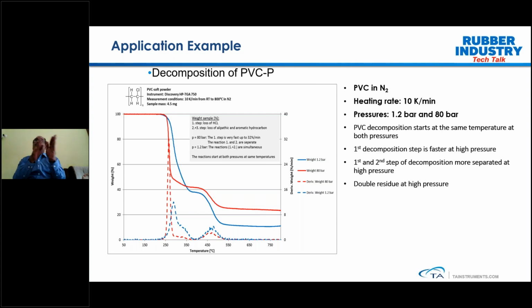And you can see clearly the two step changes of PVC. First it evolves the HCl, and then the second decomposition corresponds to the loss of aliphatic and aromatic hydrocarbons. Now, the same studies we are doing at an elevated pressure, which is at 80 bar. What we see here is that the onset of reaction is at the same temperature, but the studies we have done at 80 bar show a faster decomposition rate as compared to the studies that we performed at the lower pressure.